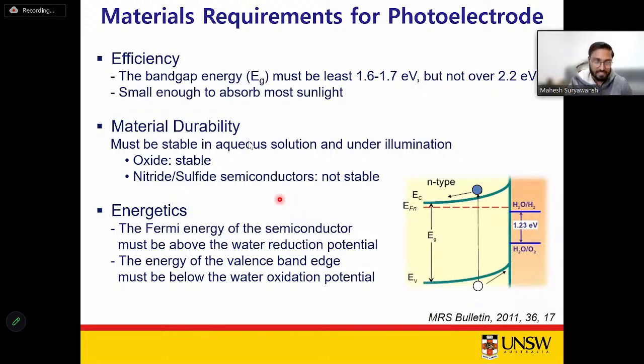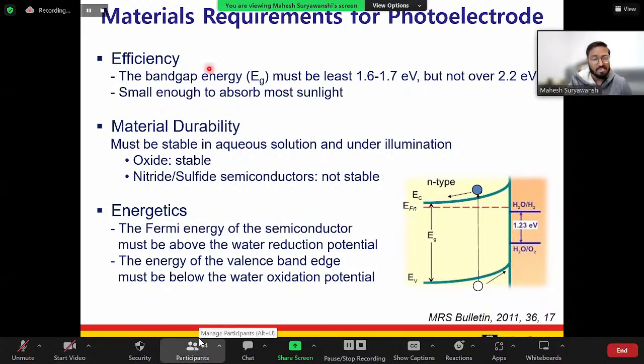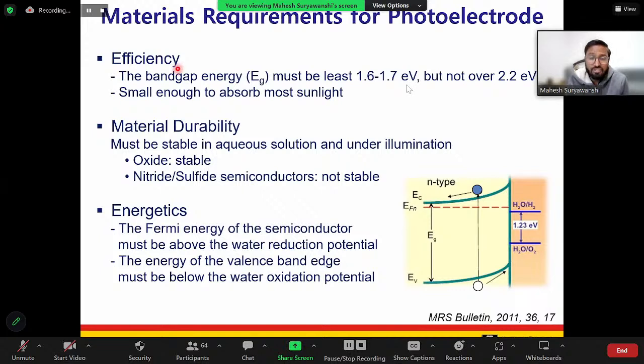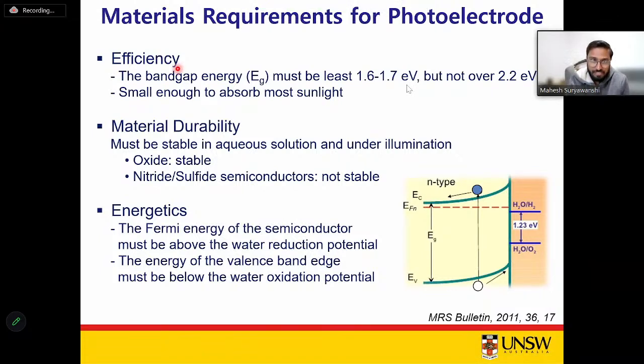But when we fabricate the PEC cell, the most important thing is the different photoelectrode materials, which are the photocathode and photoanode, and they have different requirements. First, to have a high efficiency of the photoelectrode, their band gap energy should be at least 1.6 to 1.7 electron volts, but not over 2.2 electron volts, because this is the optimal range where we can harvest the maximum of the sun's energy. It should be small enough to absorb most of the sunlight, and that's what this value represents.